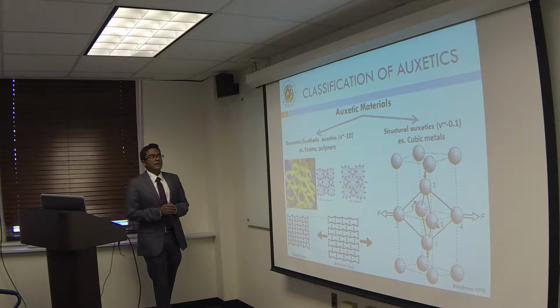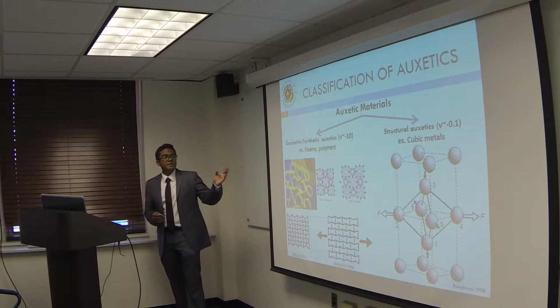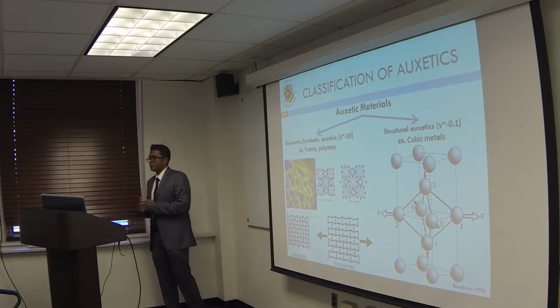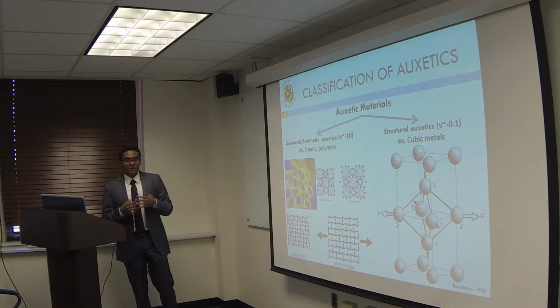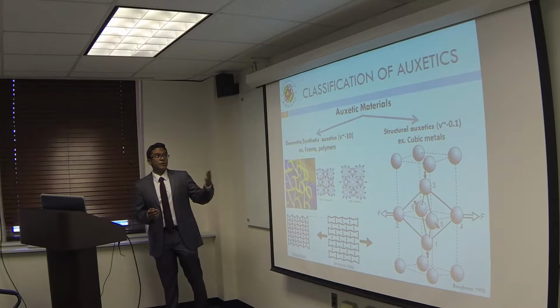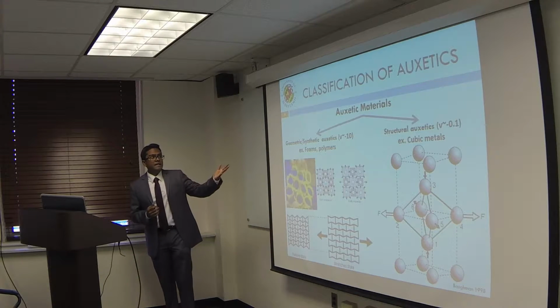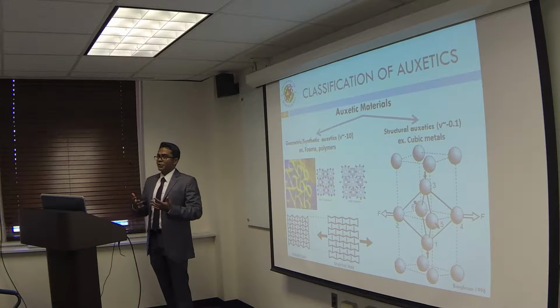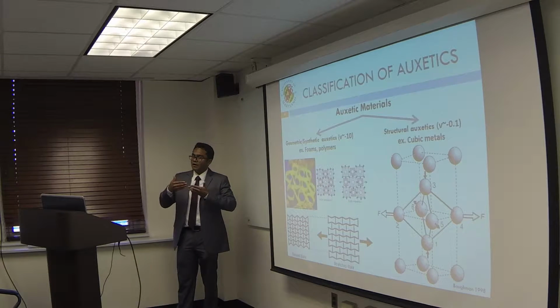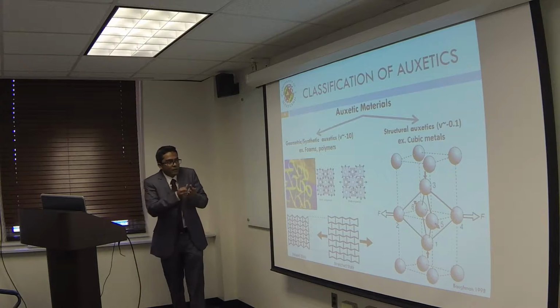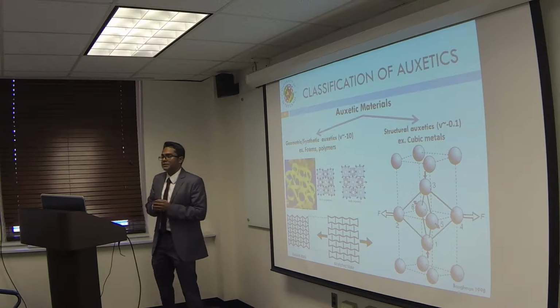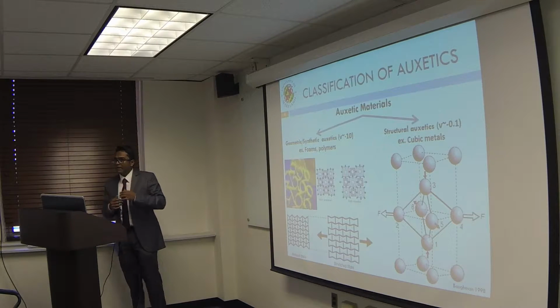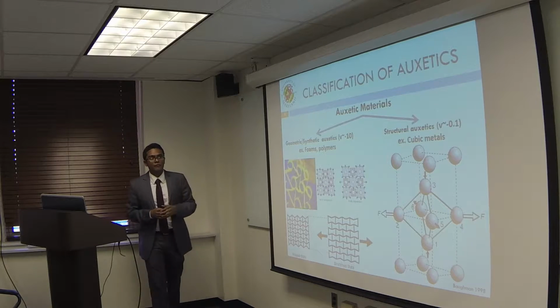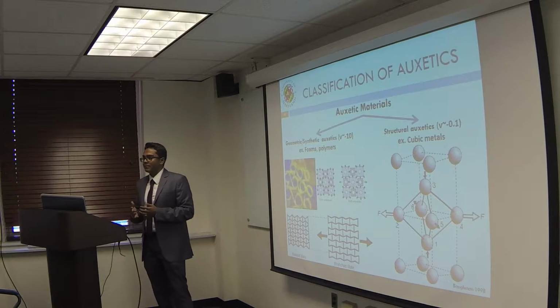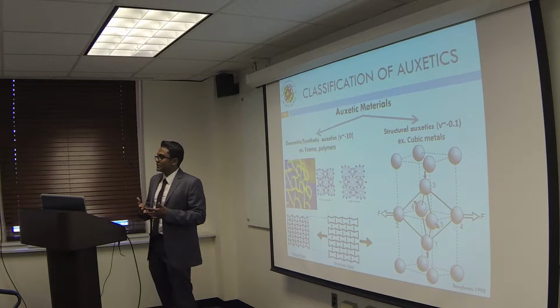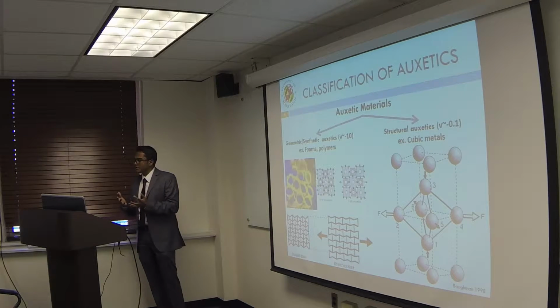Auxetic materials are broadly classified into 2 major categories. We have geometric or synthetic auxetics, and we have structural or molecular auxetics. Geometric or synthetic auxetics are usually man-made, and they exhibit a Poisson's ratio of about -10. And these exhibit a negative Poisson's ratio by virtue of how the unit cells that make up the material are linked to one another, mostly using hinges. So when you pull on them, they tend to get broader because of these hinges between the unit cells. In the case of molecular auxetics, the magnitude of the Poisson's ratio is much smaller. It's of the order of 0.1. And it's usually exhibited by cubic metals. And in this case, the negative Poisson's ratio is because of the way in which the atoms that make up the crystal lattice interact with one another.